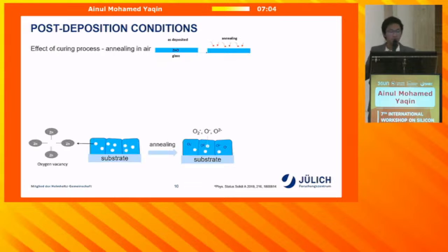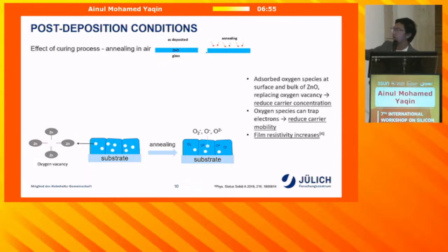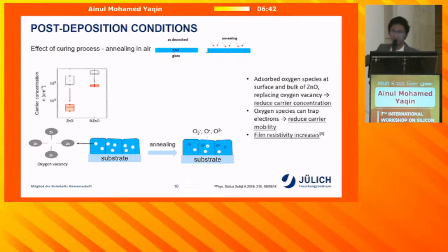Apparently, the silicon heterojunction fabrication process has a curing step, which is annealing in air after we screen print the silver metal. Definitely, this additional annealing step changes the electrical properties of the film. In the case of the TCO, usually we have oxygen vacancies, which contribute to the charge carriers. When we anneal in an oxygen-rich environment, these oxygen species can be absorbed on the surface or in the bulk, which can replace our oxygen vacancies, and this can reduce the carrier concentration of our film.